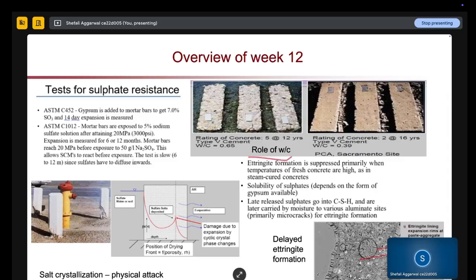Here is another example showing how water to cement ratio changes the properties of our concrete system. If the water to cement ratio is higher, you can see more white chunks forming, and at lower water to cement ratio you have a denser concrete. So you can tell more ettringite formation from less ettringite formation. This is also an example of external sulfate attack. Because of sulfate attack, ettringite formation and crack formation, your concrete is deteriorating. This is like salt crystallization, a physical attack, the same concept. Because of sulfates in your soil, more needle-like structures form, and your concrete gets disturbed.